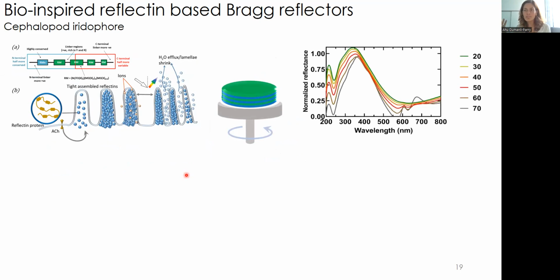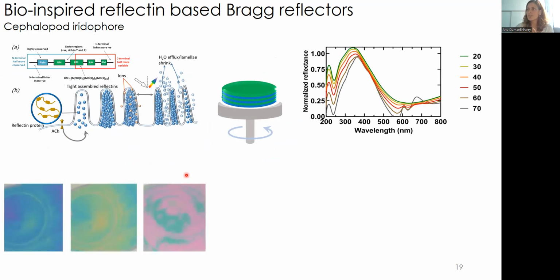And they are forming quite strikingly colored films themselves. But as a second stage, we combine them layer by layer, alternating layers of reflectin plus cellulose nanocrystals. So the results were even more striking, as you can see, like an Andy Warhol art piece. The modulation of the coloration is based on the concentration of the cellulose nanocrystals and how much reflectin we build up on it, with reflectin acting as an amplifier for the color response.